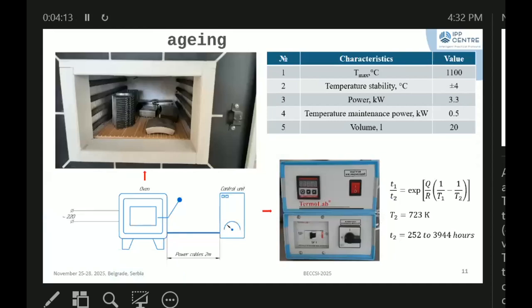A laboratory oven was used for artificial thermal aging. This process was carried out at a temperature of 723 degrees Kelvin. The aging time varied from 252 to 3944 hours, and was calculated using this relationship, this equation. Here T1 is the operating temperature, and t1 is the operating time at the operating temperature.